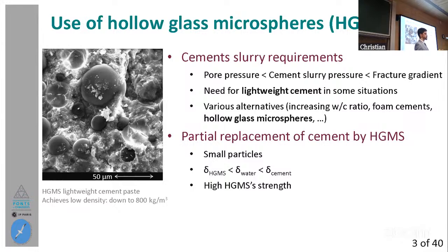This is a measure of the strength of the rock formation at each depth. In particular formation rocks in which this fracture gradient is low, we will possibly need to use lightweight cement slurries. There are many alternatives to achieve this lightweight material, among which we can distinguish those listed there, which are increasing the water to cement ratio or using foam cements. These are well known for increasing the porosity, particularly intergranular porosity, and affecting the general performance of this material.